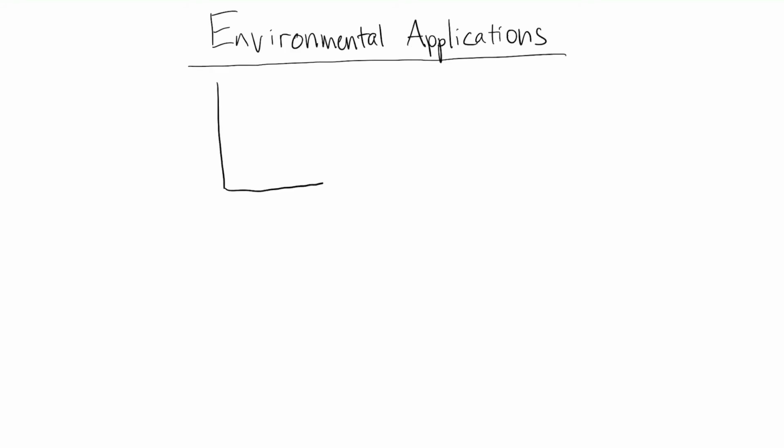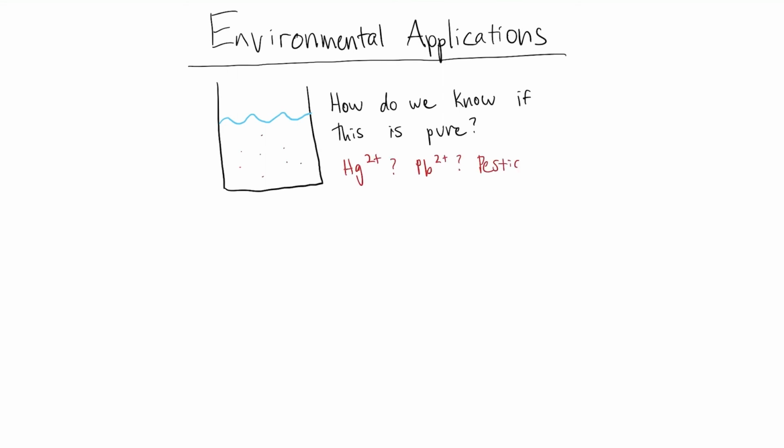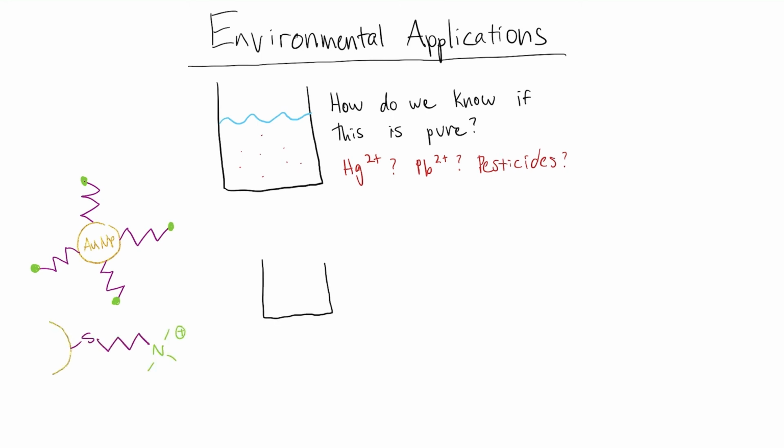Gold nanoparticles and nanowires have also been applied to a key environmental concern, contaminated water. One use of these gold nanoparticles is to act as a chemical sensor and detect different kinds of toxins in the water. Sensors like this have been developed for heavy metals, pesticides, and bacterial toxins. For heavy metal sensors that detect things like mercury, chromium, and lead, gold nanoparticles are generated that are capped with quaternary ammonium group terminated thiols.